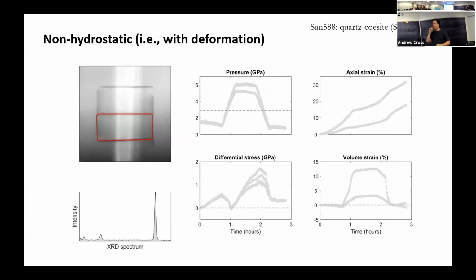All right, let's look at our non-hydrostatic comparison experiment. So again, at 900C, it's basically the same PT path. We're just going to ramp up in pressure to coesite and then ramp back down. But this time we're driving those vertical rams at a constant rate, increasing the pressure behind them by driving syringe pumps in at a constant rate. So that approximates a constant rate experiment. In this case, it's around 10 to the -5 in strain rate.